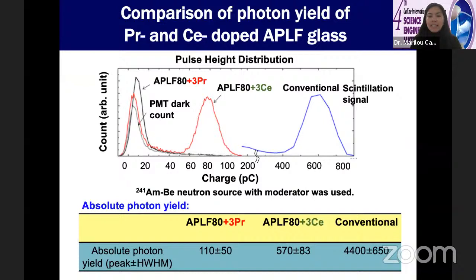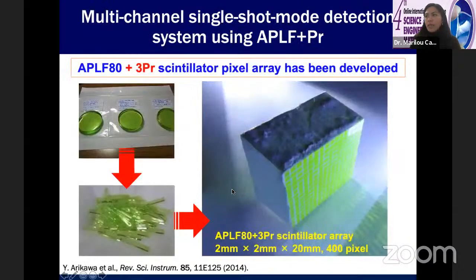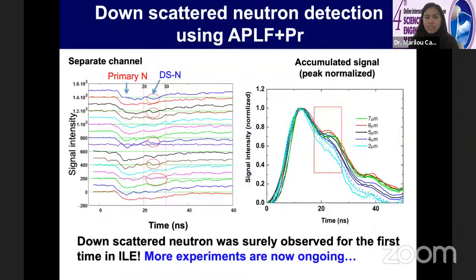But for us, the decay time is a more important factor because we can always fabricate a detector with scintillator arrays. So that's what we did. We took the praseodymium, which has the faster decay time, and we fabricated a scintillator pixel array using strips of praseodymium doped APLF. By using this array, we are able to integrate the scintillation light yield, so that even if a single scintillator has low light yield, the combined light yield will be enough for us to detect the luminescence intensity.